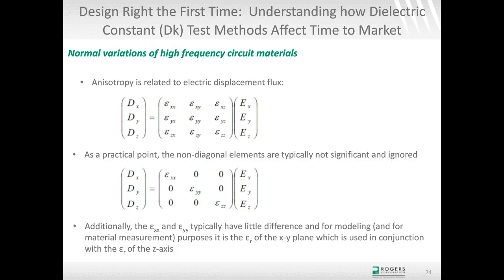There's a tensor that relates that in a mathematical sense, shown here, but what we normally do is ignore the non-diagonal elements of this array, because they are very insignificant if you look at the details. And epsilon sub xx and epsilon sub yy are usually very similar numbers, and in electromagnetic modeling software, they usually assume those to be the same number. If you get into measuring materials, you'll find that is usually a valid assumption, but it's also very difficult to measure one axis separately from the other. Many test methods can measure the XY plane much more accurately than one axis versus the other. So in general, we think of the XY plane versus the Z axis as the anisotropy difference of materials.